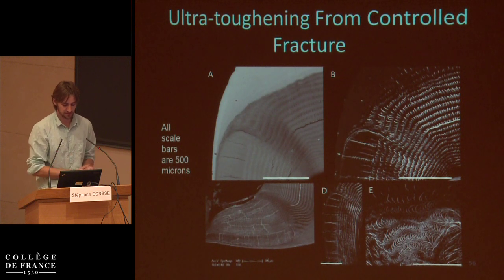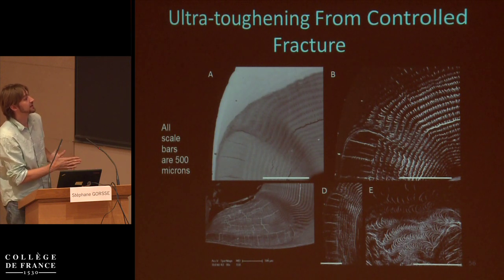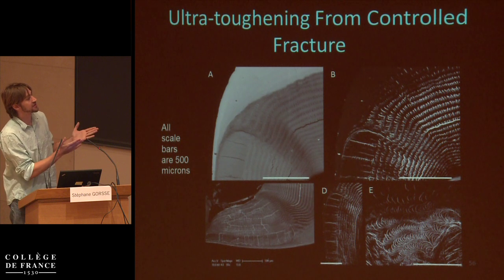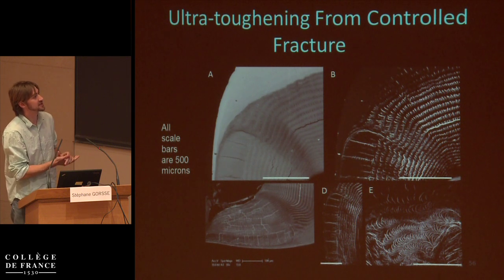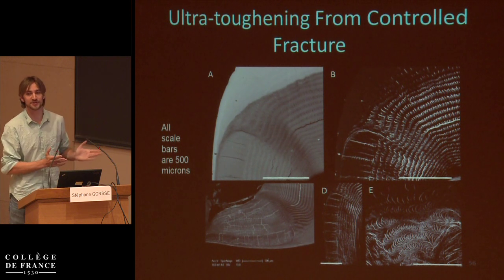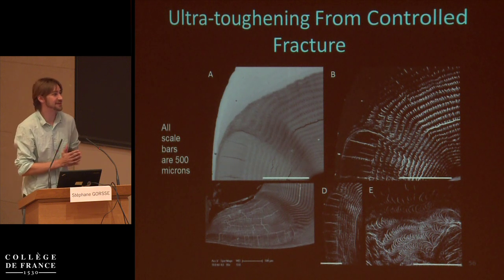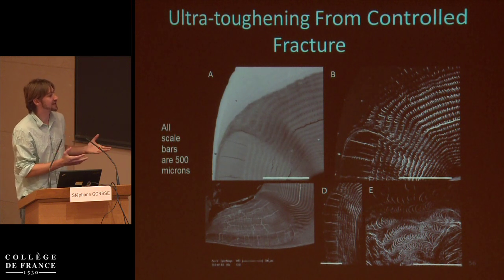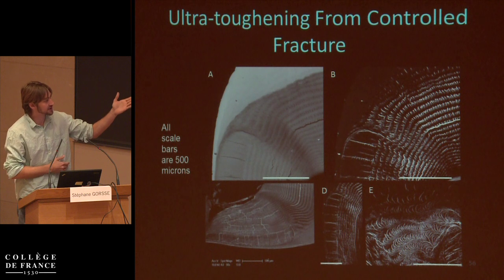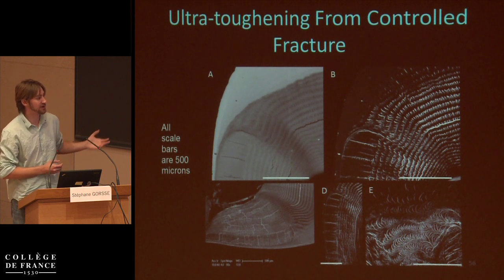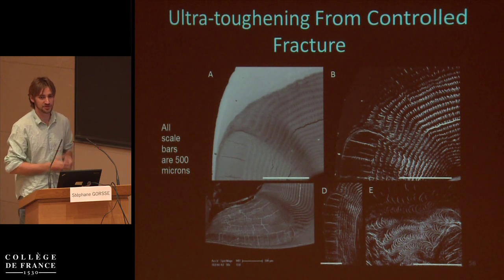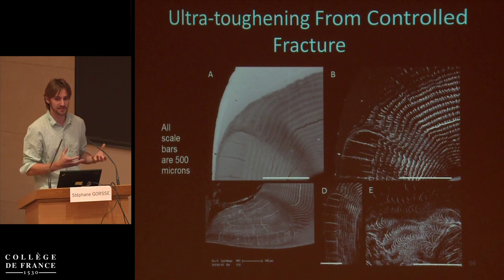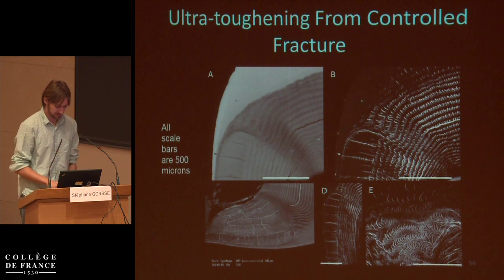And so here's basically this mechanism in action, and from these charge contrast images, you see, I don't know how to estimate this, but I don't know, square kilometers of fracture surface area. But they're just riddled with fractures, and yet if you trace any of these fractures with your eyes, not a single one of them propagates to the edge of the material. And so the structural integrity of this bulk composite is not compromised.